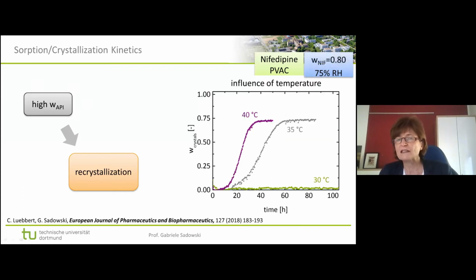More interesting is temperature. You see we have done this at 40 degrees centigrade, the accelerated condition, and at 30 and 35. And you see that this really makes a huge difference. Particularly at 30 degrees centigrade, there is almost no crystallization. This is because the glass transition temperature of this formulation, this is 0.8 drug load of nifedipine in PVAc, is indeed between here. So this sample is below glass transition and this is above. And you can really see that that makes a huge difference.